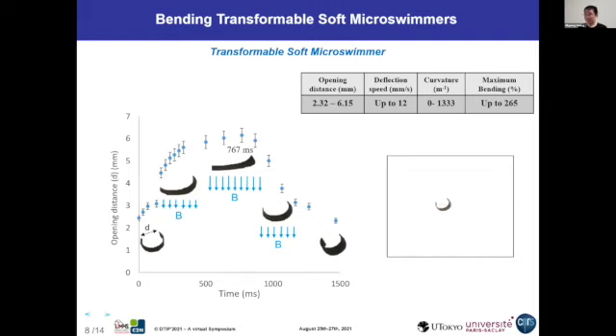And to see the morphology transformations: initially, right after the fabrication, due to the built-in stress, it deforms to a cylindrical shape with the opening distance d. By applying an external magnetic field, for example here downward, globally, these cylindrical structures become flat ribbon structures. And by removing the magnetic field, it comes back to the initial cylindrical shape, thanks to the elastic property of these structures.